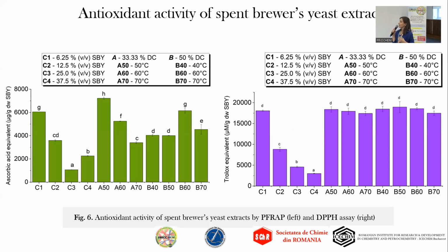To assess the antioxidant activity of the spent brewer's yeast extracts, we used potassium ferricyanide reducing power and the DPPH radical scavenging methods. Both methods show that the least concentrated sample, the 6.2% spent brewer's yeast sample, was indeed the one with the highest antioxidant activity in comparison to the highly concentrated samples.